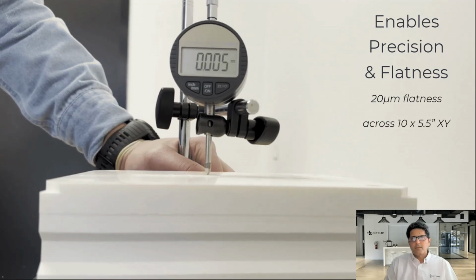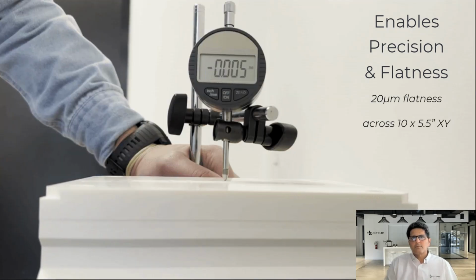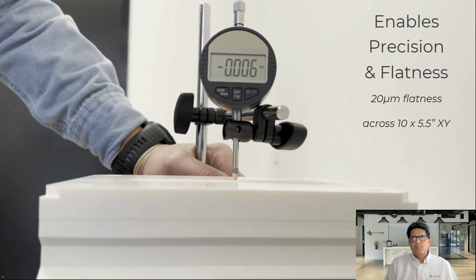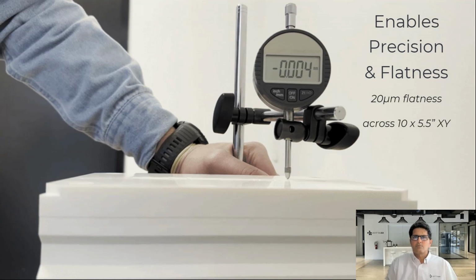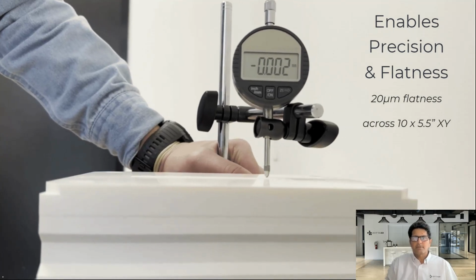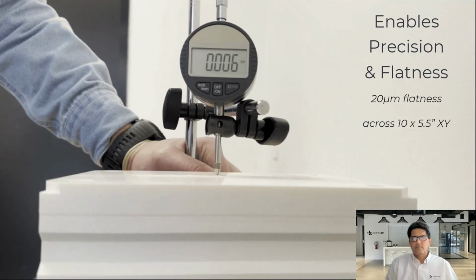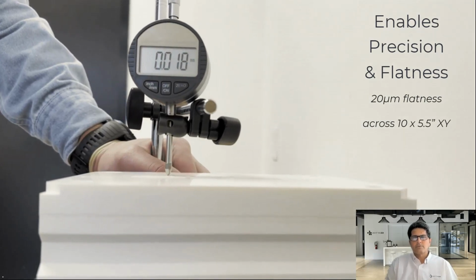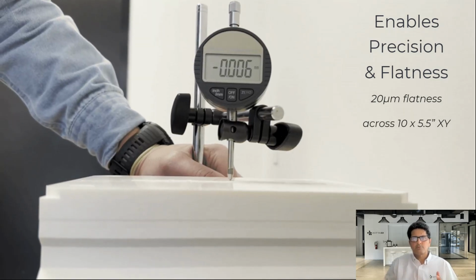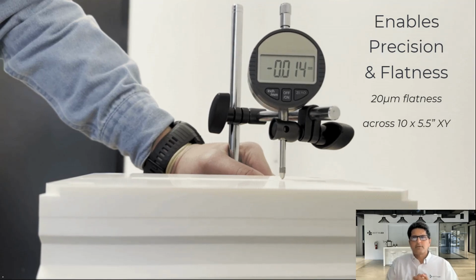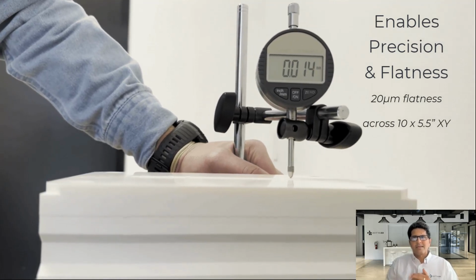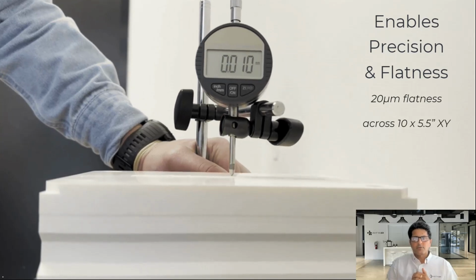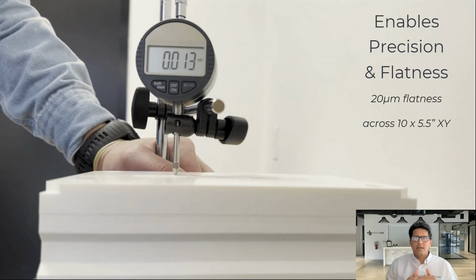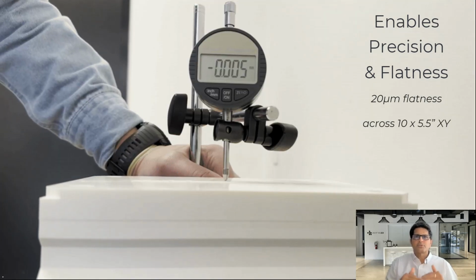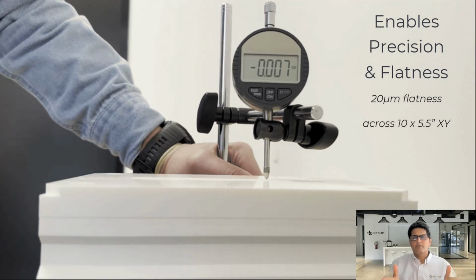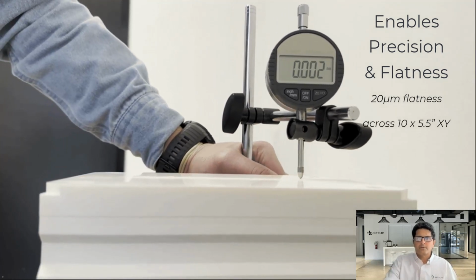It's one of the most important aspects that you can simply print a ceramic mold insert. You wash it, you cure it in the oven for 30 minutes. You can do a heat cycle if you require to, but then it can directly go into the press mold, and based on the materials that you jet, you can jet anywhere from 30 to 3,000 parts out of this. It's a great advantage just because TrueLayer does not introduce any hydrostatic forces, and we get pristine flat layers and details and accurate XY dimensions of parts that we print.